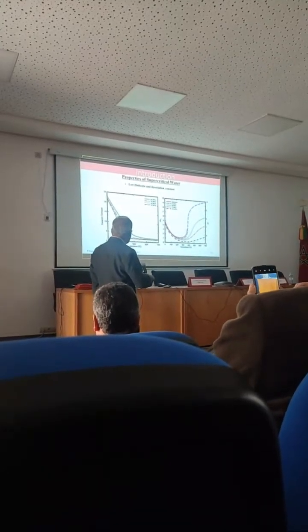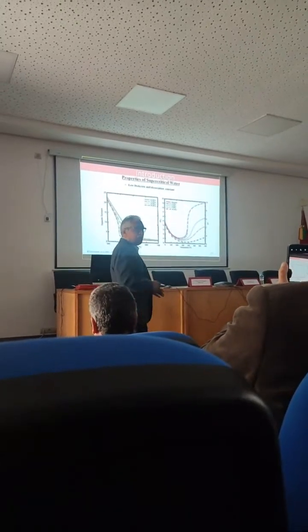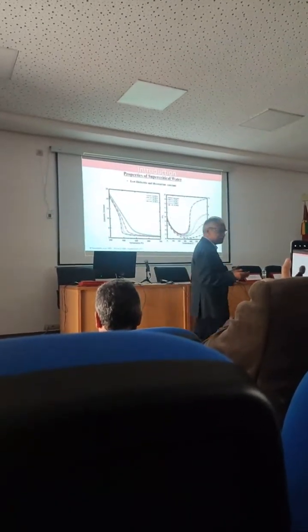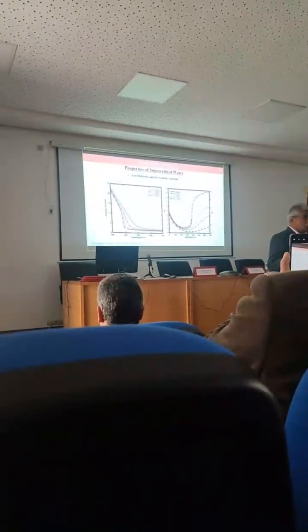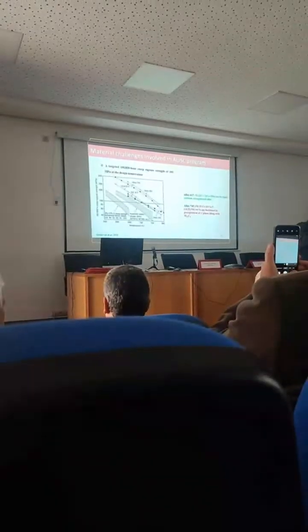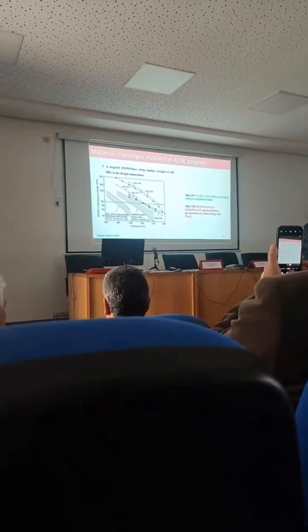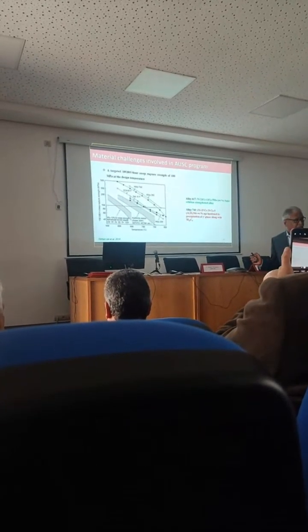I will not go into details. The dielectric constant really becomes low, and the dissociation constant changes. All are really happening in the systems. That means now we look at water differently from the corrosion point of view as compared to normal water. It is not 500 degrees Celsius, but high temperatures. The metal has to withstand the temperature. The temperature is 700, the creep, right?